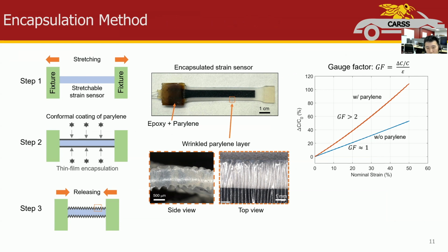Eventually, we release the sensor to spontaneously form a wrinkled Parylene layer that is stretchable. As you can see in the middle, when Parylene is under compressive strain, it will buckle to form those wavy structures. We then apply epoxy and another layer of Parylene at the connector to achieve full sensor encapsulation. Such a strain sensor can be stretched up to 50% strain with a gauge factor larger than 2 and also minimal hysteresis.